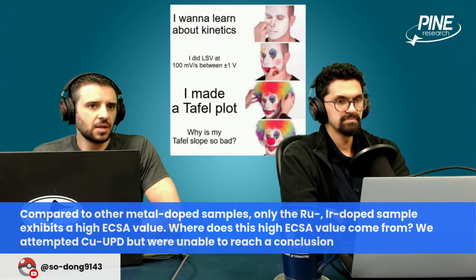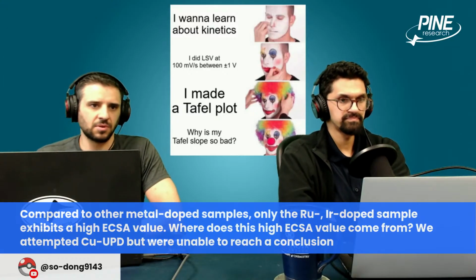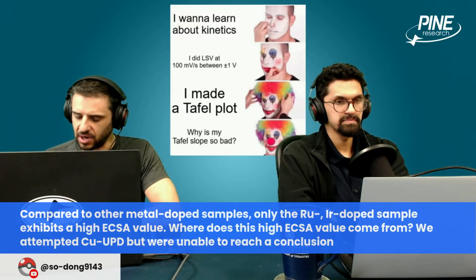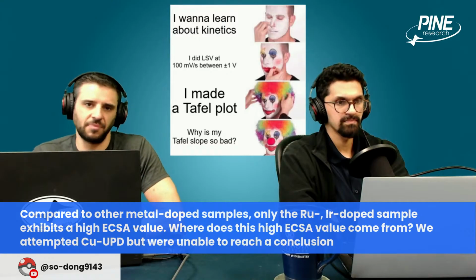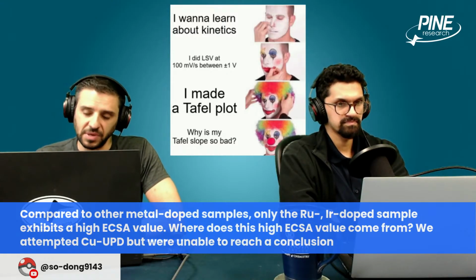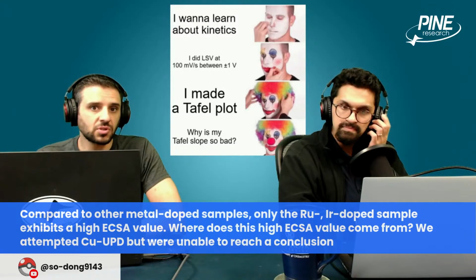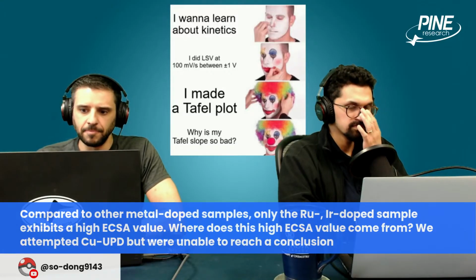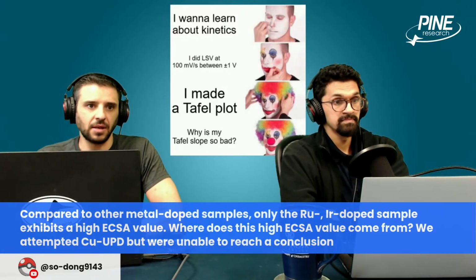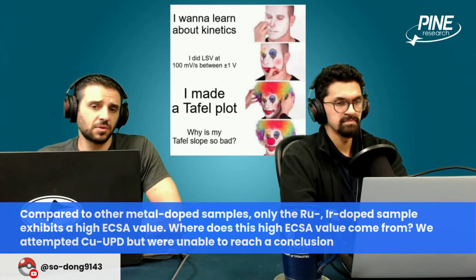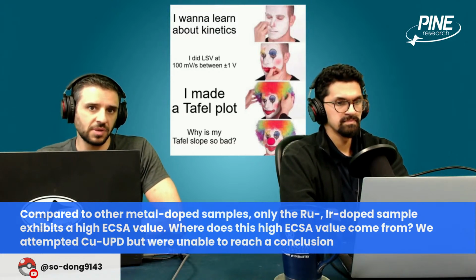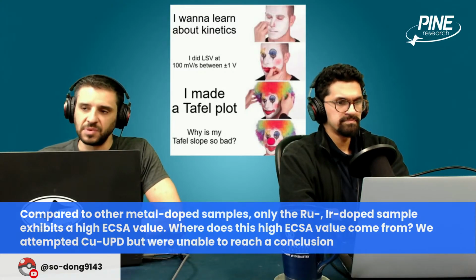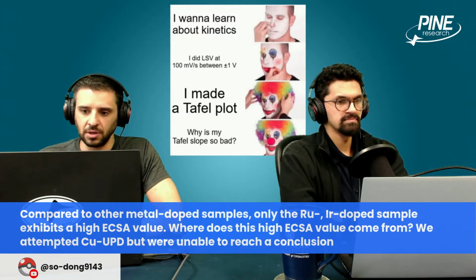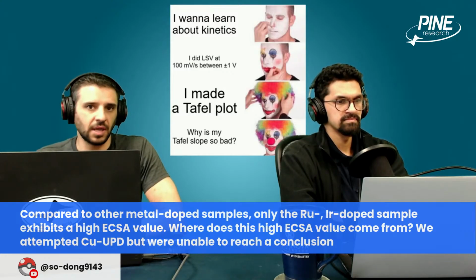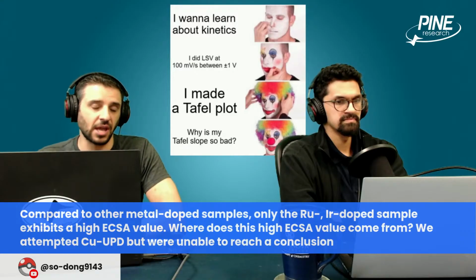Whatever the process, whether it's a sputtering process or electrochemical process or atomic layer deposition, whatever process you're using to add a dopant, whatever your substrate is, it might bond well with a ruthenium dopant and an iridium dopant. Maybe the reason your ECSA was low for the others, whether you tried palladium or something else, is that it didn't adhere well or something of that nature. That could be one reason.